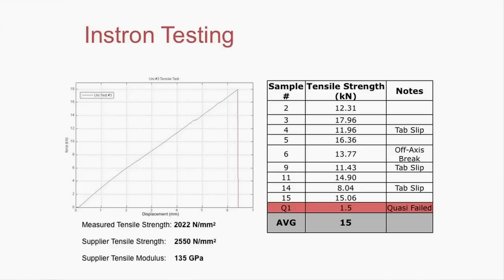On the right, there's a table which tabulates all of our findings. The quasi isotropic test, which is at the bottom, that one failed because some of the samples that are passed around are only about a half inch wide. And in order to do the proper quasi test, you need a complete strand at a 30-degree angle from one end of the clamp to the other, which would be probably about that long. And since we only have small little segments of fibers that fit together, it failed because there's not enough fiber running across to actually take any load, so it's not even quasi. But the other tests, most of them were very successful, and then there were a few little mishaps just from the tab slipping off and off axis from just user error.